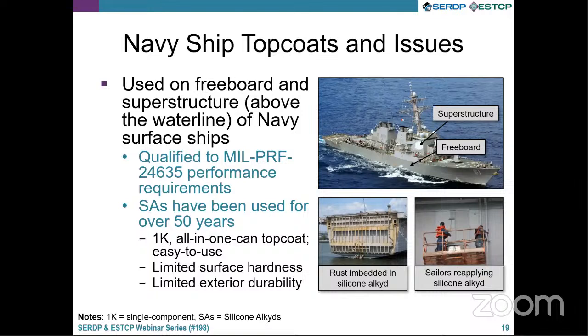Historically, and so I would say more than 50 years, silicone alkyds have been the technology of choice. And the reason why silicone alkyds were used was because they were a single component system, which that single component is designated as 1K, which is an all-in-one can solution. So similar to wall paint that you would apply inside your house, but a higher performing technology than wall paint that we buy at Lowe's or Home Depot. But this technology was very easy for sailors to use, specifically for forming touch-up and repair, as I show in the bottom right photo. But it had some detriments. And some of the big problems with it were that even though it was cross-linked, the surface remained relatively soft.